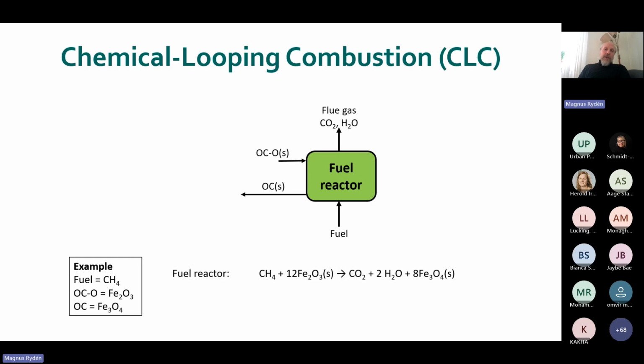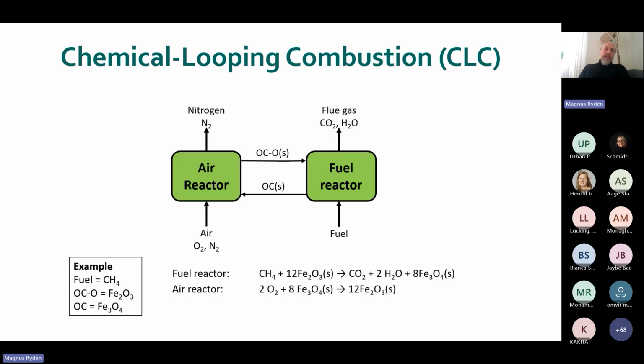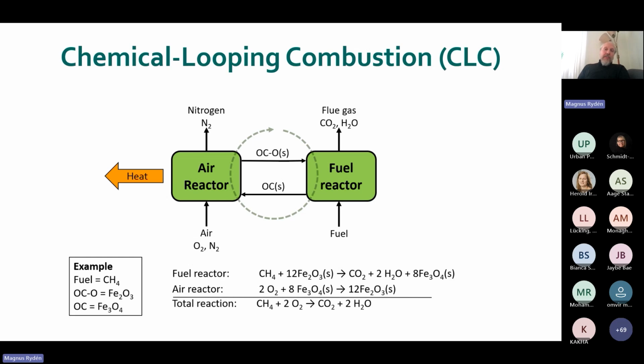And this reduced oxygen carrier we can take to a second reactor vessel. This is also a fluidized bed, which we then fluidize with air. And at proper conditions, this means that the reduced oxygen carrier will be oxidized and we will get back our hematite. If we do this in a circular fashion, then the total reaction of this two-reactor system will be combustion of our fuel with pure oxygen. Heat is generated in the air reactor, while the fuel reactor is largely adiabatic.